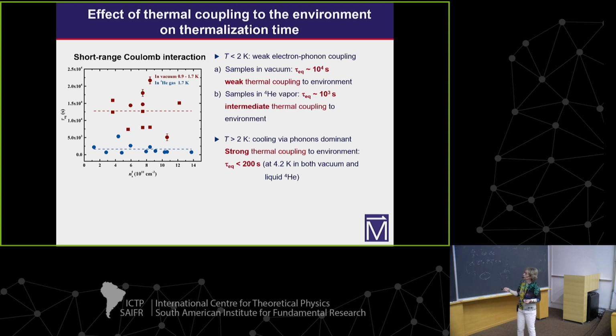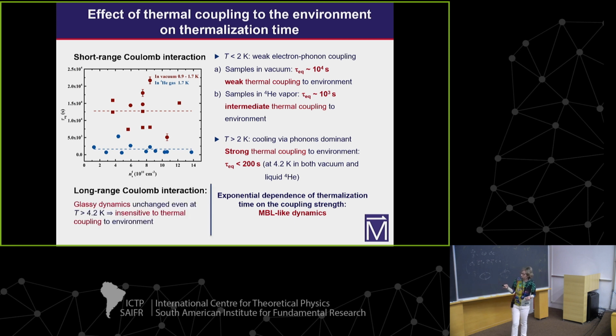So what we found is basically an exponential dependence of thermalization time on the strength of the coupling, which is exactly what you expect in MBL-like dynamics. In contrast, in the glassy case, in the case of long-range Coulomb interactions, we obtained the same results at temperatures up to 6, 7 Kelvin. There was really no difference. So this glassy dynamics is insensitive to thermal coupling to the environment, which is exactly what one expects.